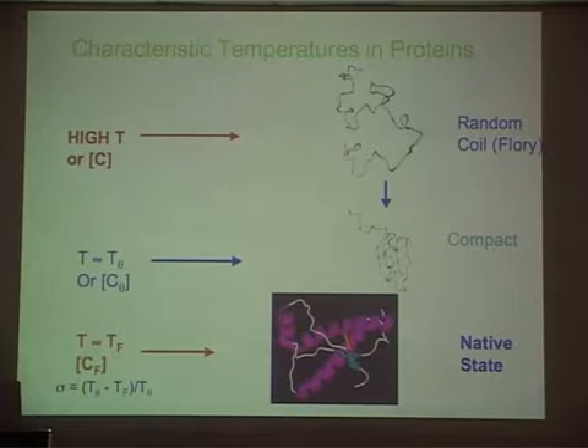One of the parameters, which I will not talk about today, that we introduced now nearly about 19 years ago, I think, is that if these two temperatures, collapse and folding temperature, are pretty close to each other, then the folding is most efficient, because under those circumstances, it's extremely unlikely that the protein would populate anything that would hang around long enough for aggregation to actually proceed. One other thing is that this transition from high temperature to T theta is nominally thought to be second order. It's continuous. Free energy is continuous, whereas this transition, in fact, is first order, but mildly so. It's not strongly first order. It's weakly first order.